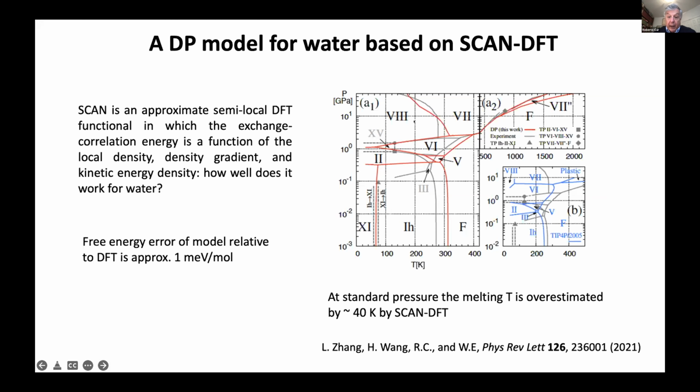with this potential. One additional thing that I want to say, in these high pressure phases, for instance, here, one goes from a system that is a standard crystal to a superionic crystal, that is this ice VII, and eventually the fluid here is an ionized liquid, different from the liquid at ambient pressure. Let me move on.